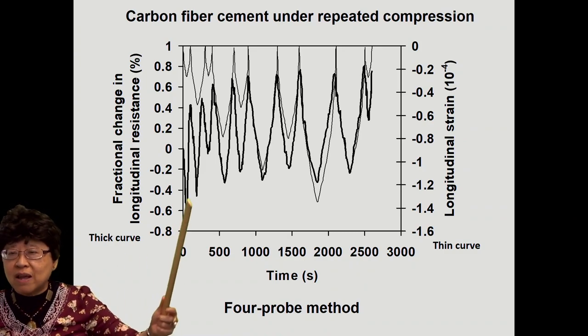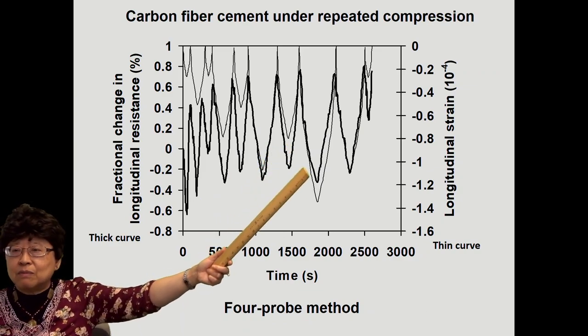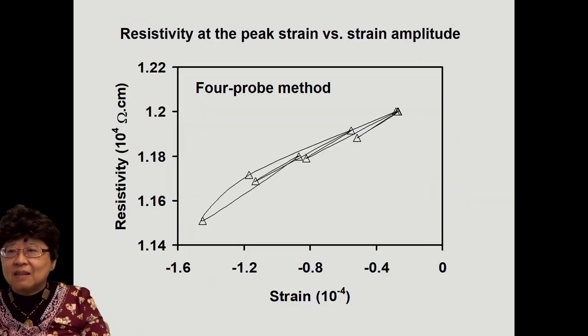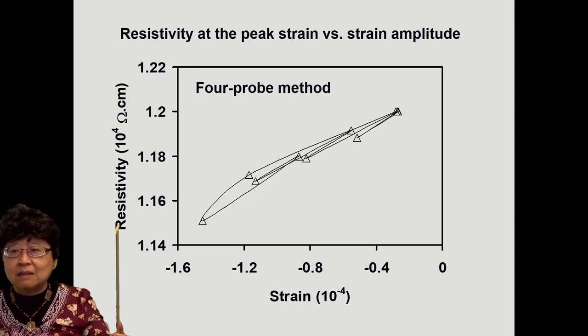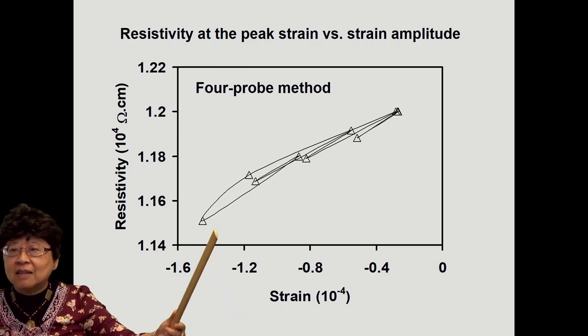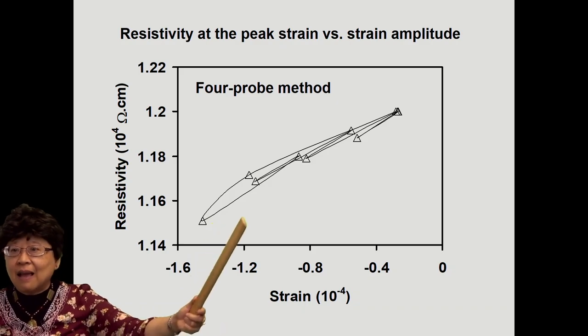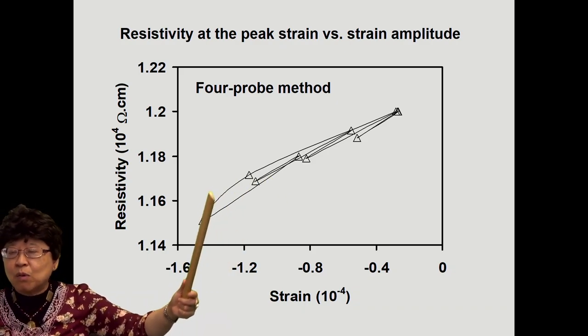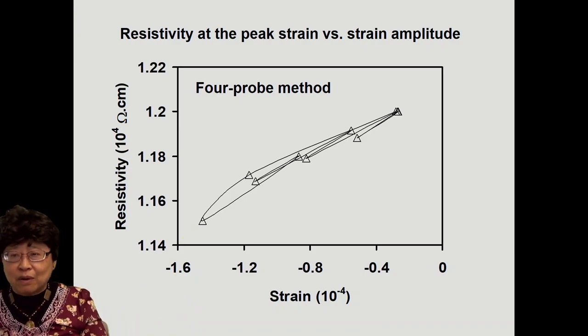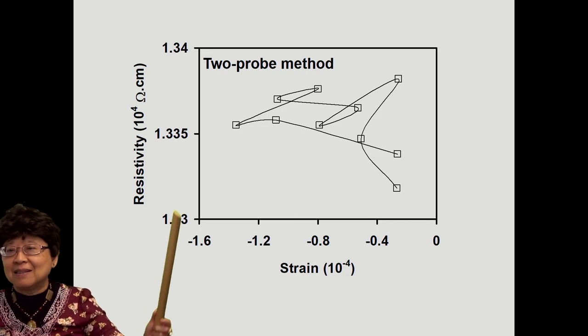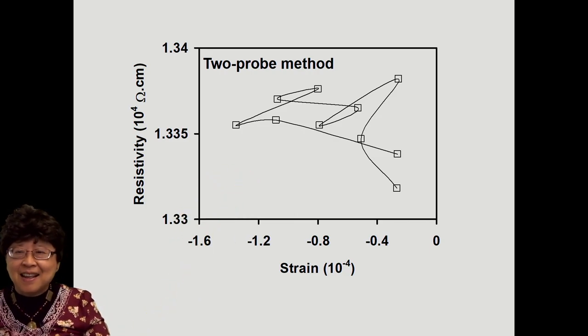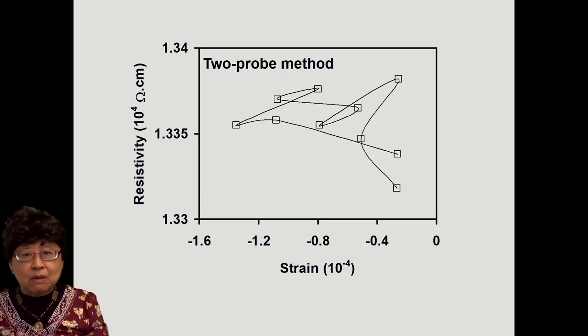And every time one strains, that is one compresses, the resistance goes down. Okay. And we can plot the resistivity at the peak of a cycle versus the strain at the peak of a cycle, connecting the data points chronologically. And we find that there is very little hysteresis, and it's more or less linear. Okay. And so it really works. And this utilizes the four-probe method. But if one uses the two-probe method, it does not work. Okay. And that's an illustration of how important correct electrical measurement is. Even if one is not an electrical engineer, one needs to know such electrical measurement techniques.